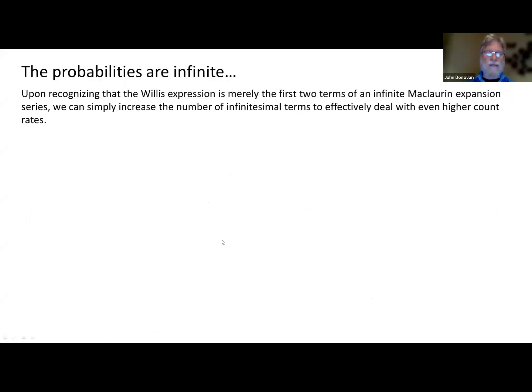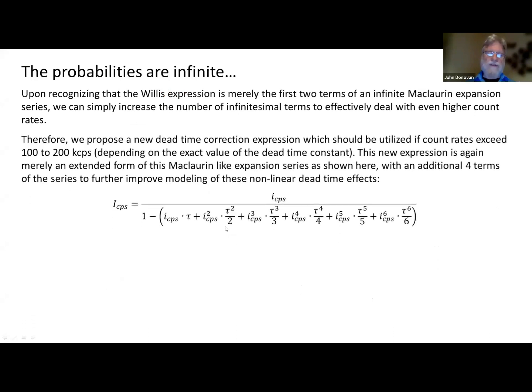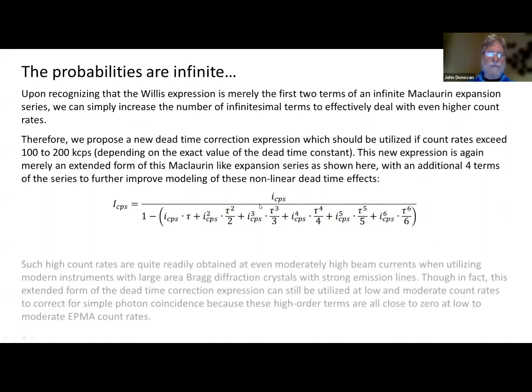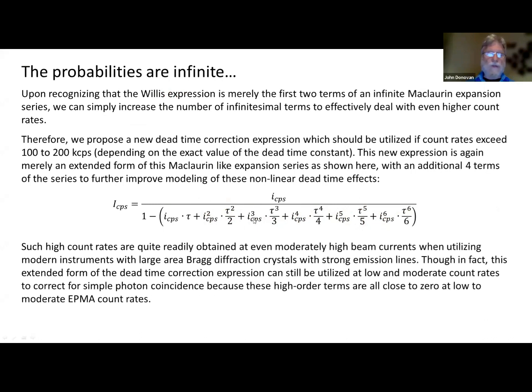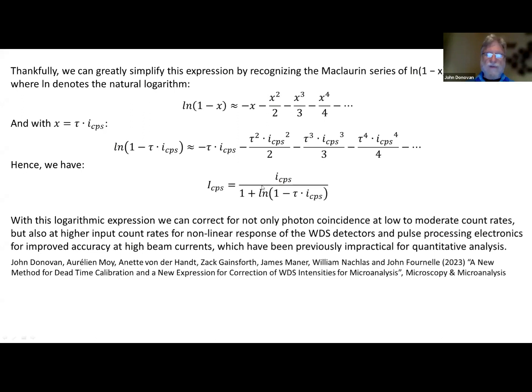Okay, let's keep going, because we realized that the quadratic term is actually a Taylor series. It's a Maclaurin expansion series, and that can be taken out to infinity. I took it out to just 6 places and tried it, and it worked even better. But then Aurelien Moy pointed out to me that we can do this very simply. We can express that infinite series as a log, and so we did. This was published last year in Microscopy and Microanalysis.